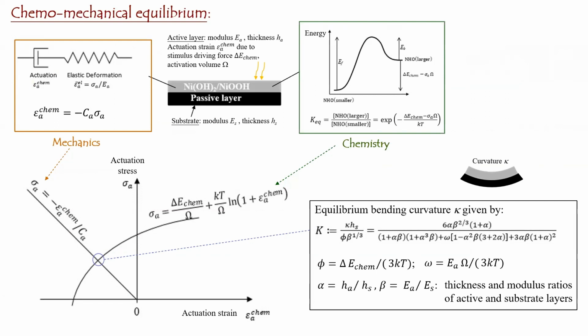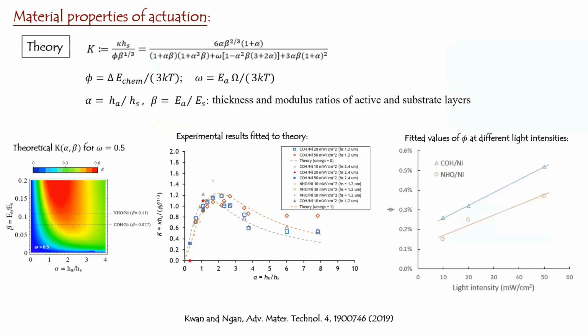So you also need the chemistry characteristic. So the chemistry characteristic will be this curve, and then the elasticity will be that curve, and then the crossing point will give you the equilibrium, which is equilibrium between the mechanics and the chemistry. So this opens up a new topic, which is called chemomechanical mechanics, which is quite interesting. And then if you, again, further massage the Timoshenko equations, you can show this equilibrium condition is given by this. And then using that equilibrium, you can back out material properties of the actuation.